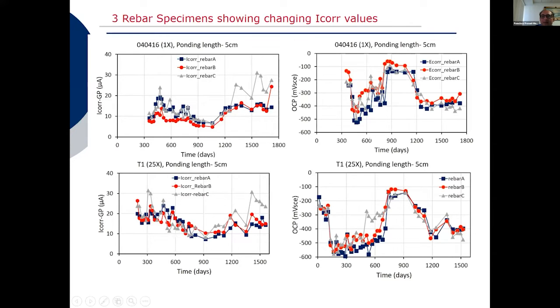That happened on both of them, and I'm going to use this particular plot on the left to describe how we obtain the mass loss. Each consecutive value was the average of the two measurements, and we multiplied that by the time elapsed in seconds, and from that you can obtain the charge. You repeat that for each one of the pairings, and you can calculate the area under the curve, converted to charge. You use Faraday's law, and from there you can obtain the mass loss.